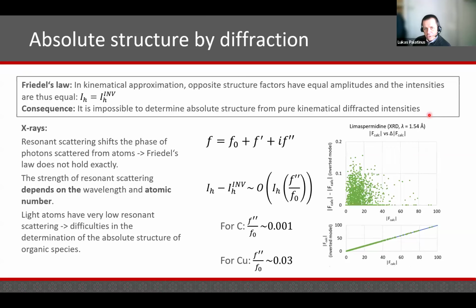Unfortunately, determination of absolute structure by diffraction is all but easy. The reason is that the diffraction is, to a good approximation, centrosymmetric. That's called Friedel's law, and it means that within the kinematical approximation, without any other information or any other effect, the absolute structure cannot be determined purely from diffraction.